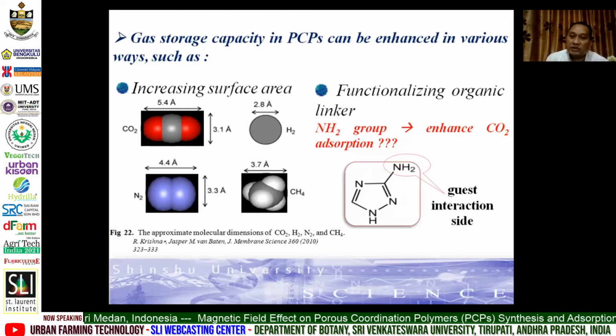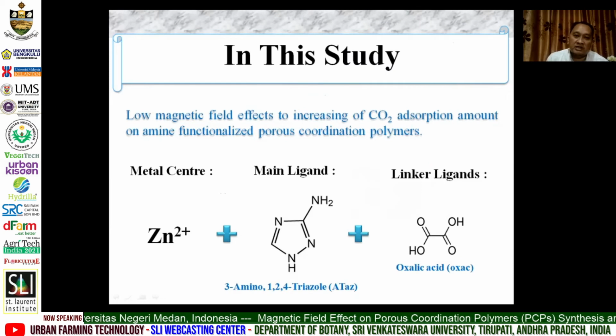But the second strategy is functionalizing the organic linker. Some papers reported that the amine group can enhance this carbon dioxide adsorption. So in this triazole ligand, we inserted the amine group as the gas interaction site with the carbon dioxide to increase this carbon dioxide adsorption. Okay, in this study, we changed the triazole to 3-amino-1,2,4-triazole, and then we also use the same first ligand, oxalic acid.